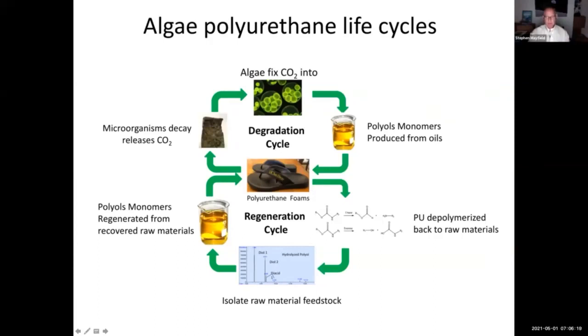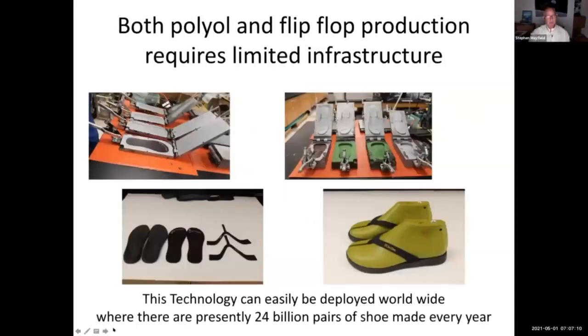But a much more efficient way to do this is we simply take the products back in. You wear your pair of shoes for a couple of years, you finally wear them out, you send them back to us, we bring them in, we grind them up, and we depolymerize those polyurethanes with enzymes. We recapture the starting diols and diacids, and then we use those to resynthesize new monomers and use those monomers to make new products. If we do this, what we say is we have a conservation of chemical energy. We're not putting this all the way back to CO2 and then having to use photosynthetic energy to recapture it. The enzymatic release of these requires very little energy. You know how efficient enzymes are. That means we can very efficiently recapture these and apparently infinitely recycle them, because every time we go through a depolymerization and a recapture, that gives us an opportunity to clean up, to throw out the parts of the monomers that have been degraded.